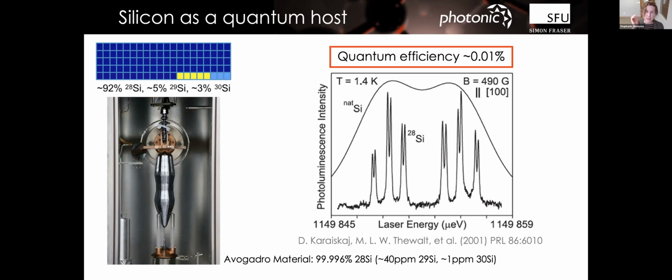The other center that would have been known around this time was erbium in silicon. That has a completely different set of challenges with it. It's a very long-lived radiative object. It does have the efficiency, and it is in telecom, but it's like a millisecond emission lifetime. So if you're looking for high rate or high coupling efficiencies, we're trying to look at a few different options.